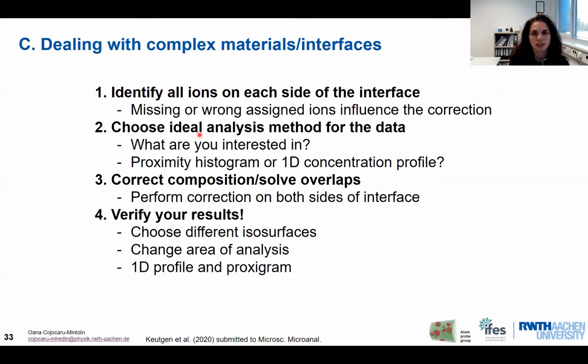Then we need to choose the ideal analysis method for the data. So you need to ask yourself what you are really interested in. Do you really want to perform a proximity histogram or 1D concentration profiles? Then you need to correct the composition and solve the overlaps, and this correction needs to be done on both sides of the interface. And of course, you need to verify your results at the end. So you need to choose different isosurfaces, change the area of the analysis, compare the 1D concentration profiles with proxigrams, and always double check that your results are robust.